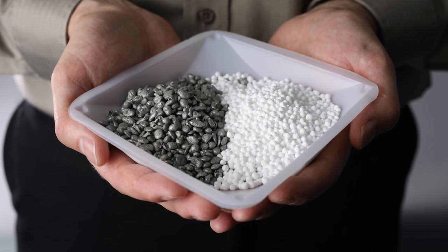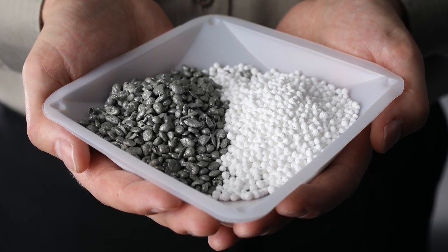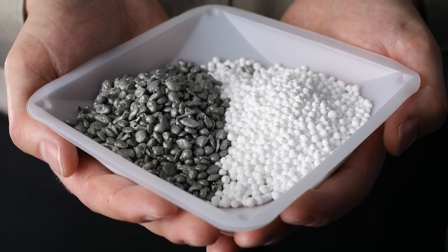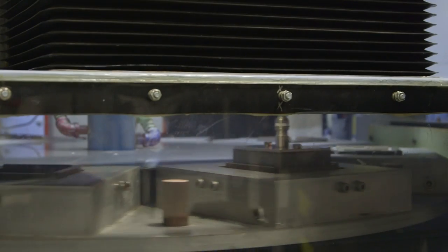To charge, you force current through the system. That prompts the metal normally in the top layer to jump back into the electrolyte, swim to the top, and recombine to regenerate the top layer. This is tantamount to what we call electro-refining in metallurgy. By charging the battery, you essentially return it to its pristine initial state, which may account for why we can cycle these things for thousands of cycles without loss of capacity.